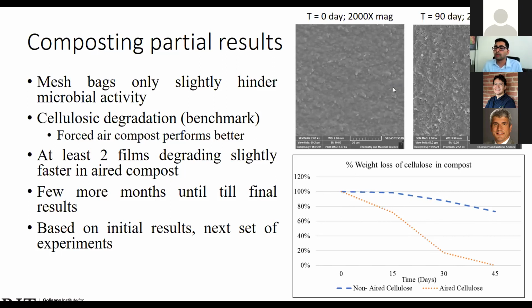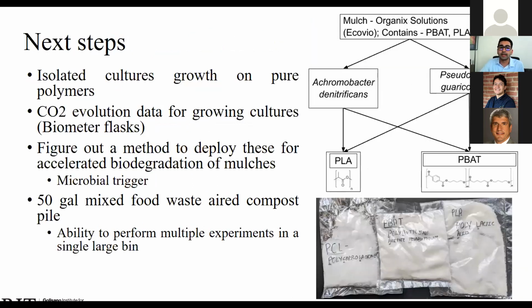One of the films, this one, is a T0 sample, which has no biodegradation, there's no surface change as seen here. And there's some amount of surface change as seen in this particular image after 90 days. And finally, based on the initial results, we plan to set the next set of experiments on composting. And I'll talk about that in the next few slides.